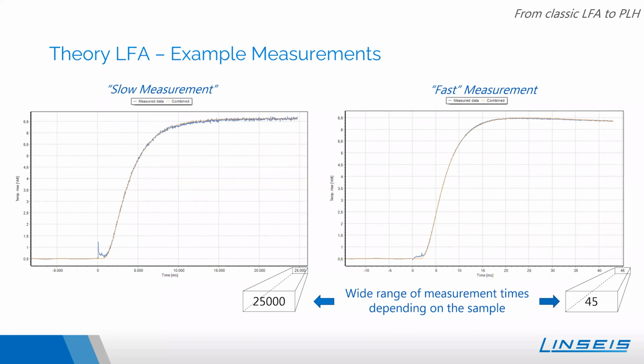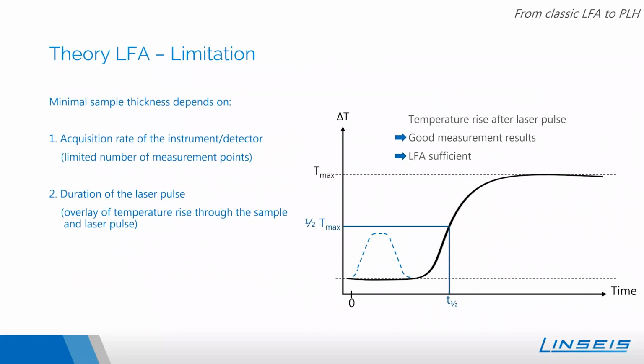So what matters is the ratio between the thermal properties, thermal diffusivity or thermal conductivity, and the thickness of the sample. And this will result in the measurement times. This experimental setup works really well as long as the time scale for the measurement is not too short. But the higher the thermal diffusivity of your sample gets and the thinner the sample gets, the bigger the measurement error gets.